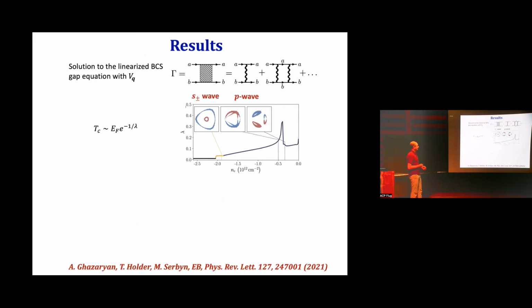Okay. So, to show you the details, we've done the calculation. What you get as a function of the hole density is that at very high hole density, where the Fermi surface is just a single warped circle, you get nothing. This is basically the log of Tc. But then beyond a certain density, you get this bump in Tc. Then it rises to this very sharp peak, the van Hove singularity, where the Fermi surface reconnects.